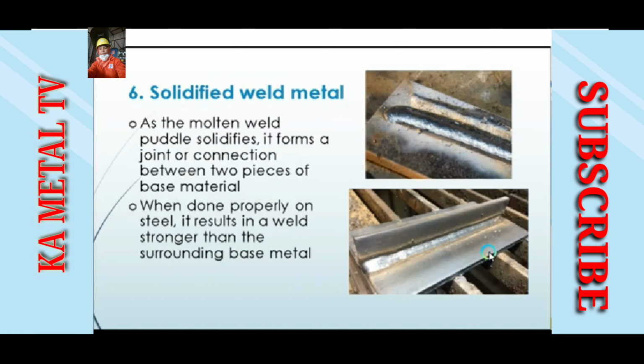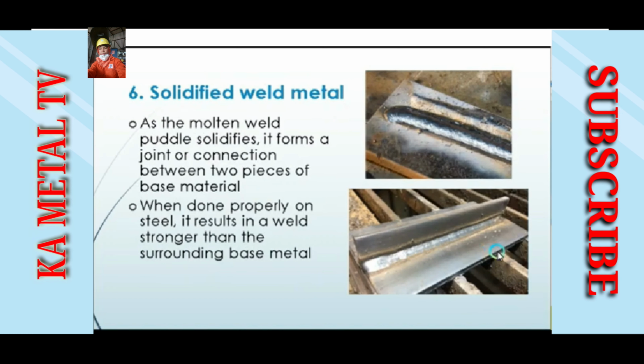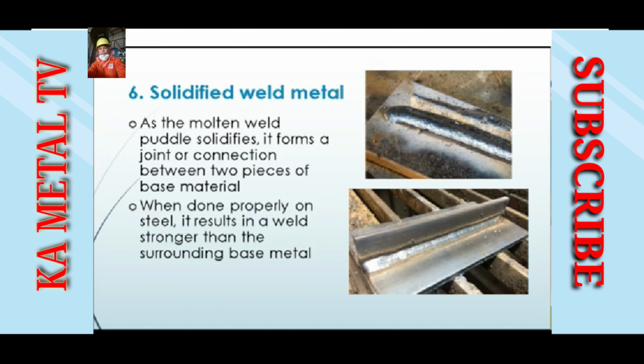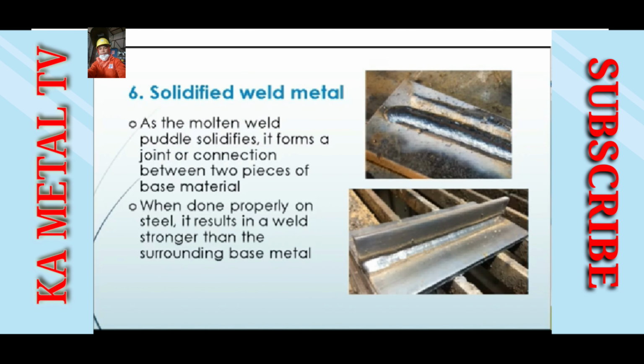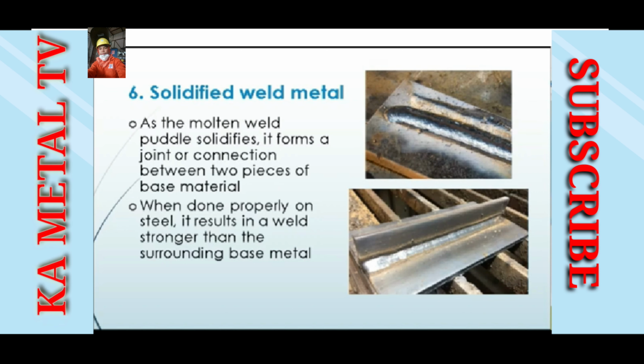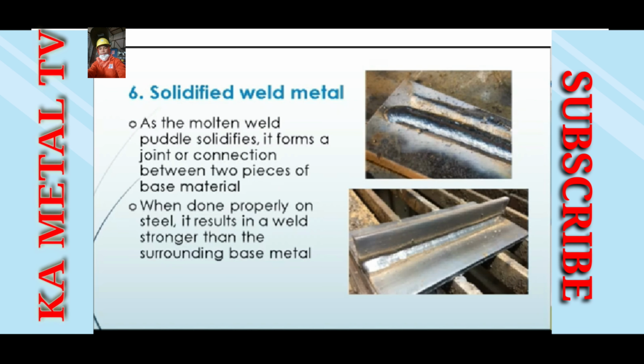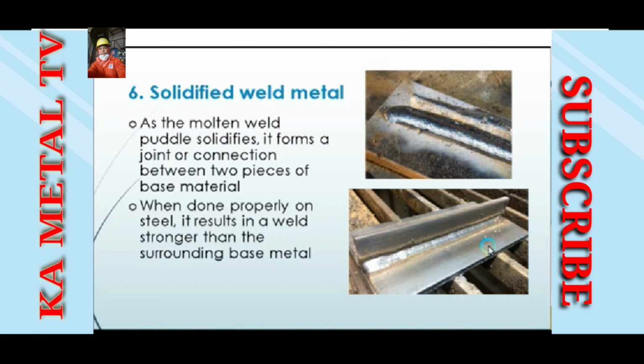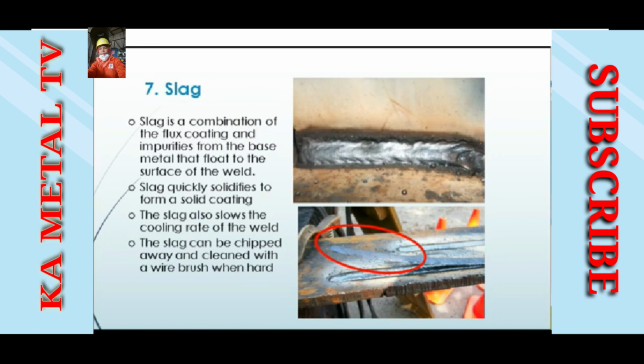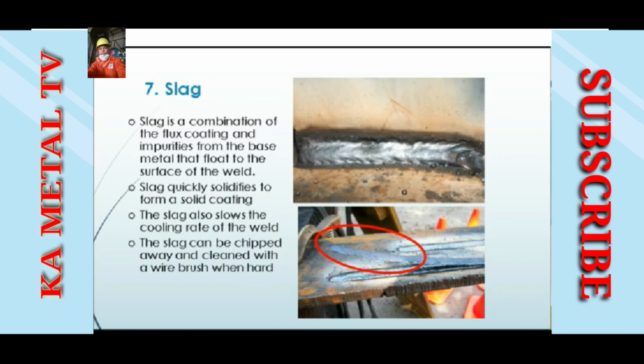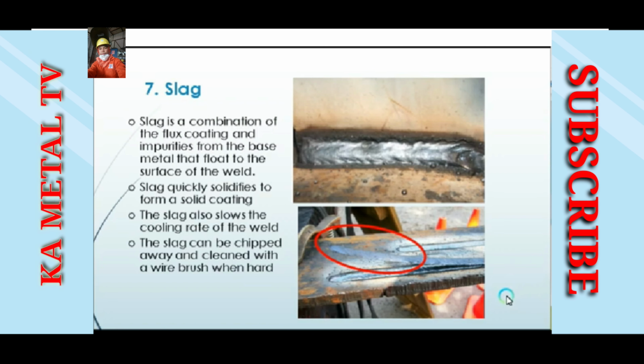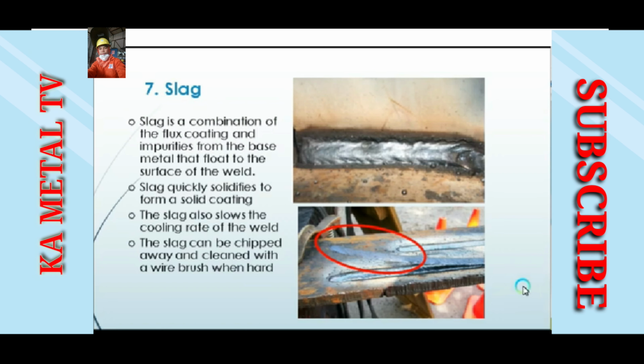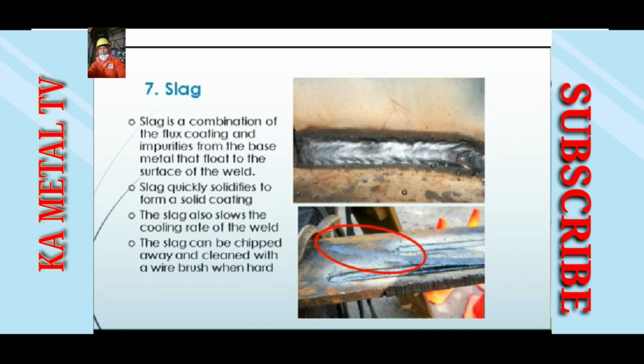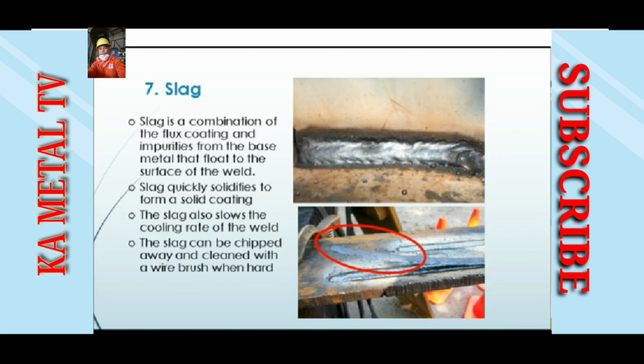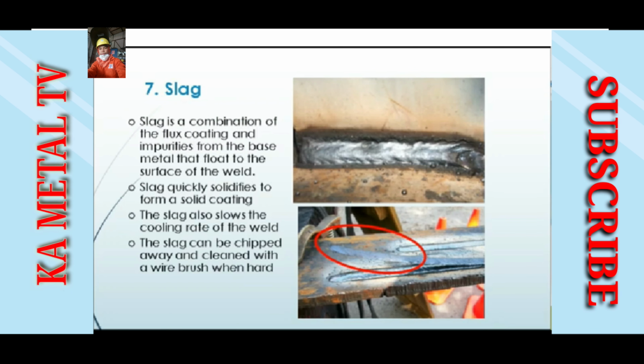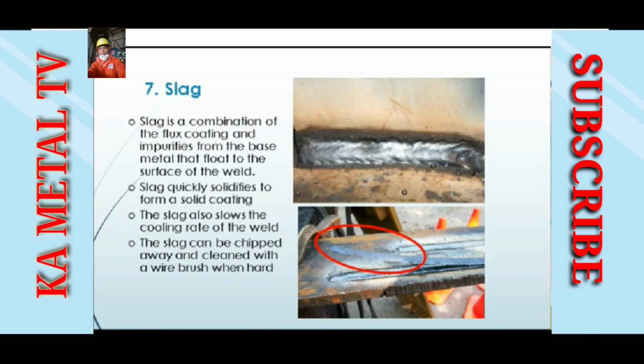Next is solidified weld metal. As the molten weld puddle solidifies, it forms a joint or connection between 2 pieces of base material. When done properly on steel, it results in a weld stronger than the surrounding base metal. Let's see slag. Slag is a combination of the flux coating and impurities from the base metal that float to the surface of the weld. Slag quickly solidifies to form a solid coating. The slag also slows the cooling rate of the weld. The slag can be chipped away and cleaned with a wire brush when hard.